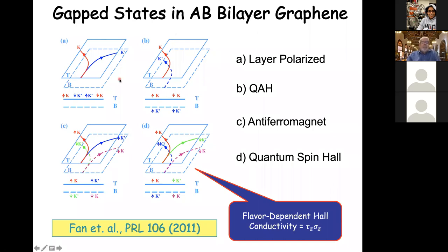And here I am emphasizing what I hid somewhat so far, that there are low energy states at two different momenta related by time reversal symmetry in graphene, labeled here K and K prime. Generally people refer to this as valley, valley K or valley K prime. So it's another pseudospin. And so it turns out that, when you have these sublattice or layer polarized states, you can do this, for example, as in cartoon A in this picture, simply by adding a gate electric field to push electrons into the top layer instead of the bottom layer. So this state depicted in A can be a single particle state.